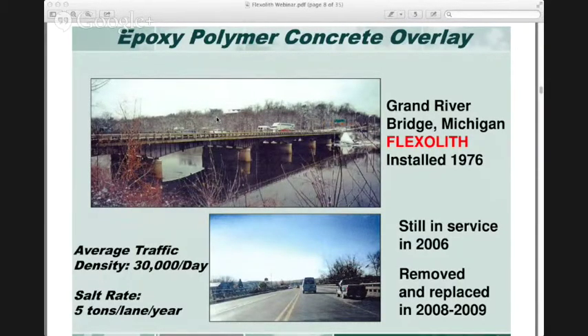Back in 76, the traffic density was something in the range of 30,000 vehicles per day. So presumably it was considerably higher by the time they removed it. And with a salt application rate of about 5 tons per lane per year, it was a real good test for this application, and this bridge held up extremely well over the 30-year period. Next.